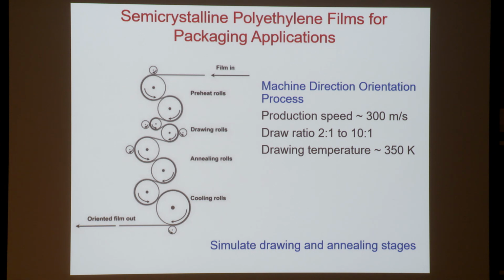So we will try to simulate at the atomistic level with molecular dynamics the process whereby such films are formed. These are formed by the so-called machine direction orientation process. Here comes the polymer, the film in. It is preheated, and then it is subjected to drawing in these drawing rolls, which move at different velocities. And the draw ratio can be from 2 to 1 to 10 to 1. After this, it comes through annealing rolls, which stabilize the film, and then cooling rolls. The production speed is quite high, 300 meters per second, and the drawing temperature is below the melt temperature.